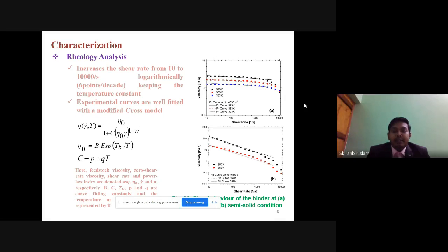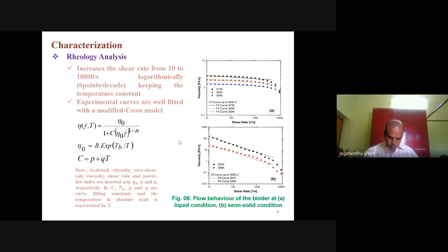Rheology analysis. Rheology analysis shows us the flow behavior of the material, and here we analyze the flow behavior of the binder as well as the feedstock. Two graphs are presented here for the binder at two different temperature levels. First one is at the higher temperature where the binder is completely liquid, and in the second one the temperature is such that one of the binder ingredients starts to solidify. Here we have used a modified Cross model to fit these graphs, and from these two graphs we can see they have a shear thinning behavior. With increasing shear rate, viscosity is dropping.